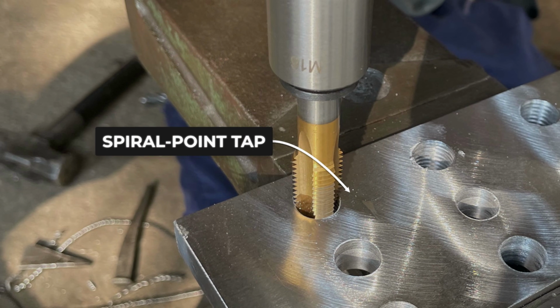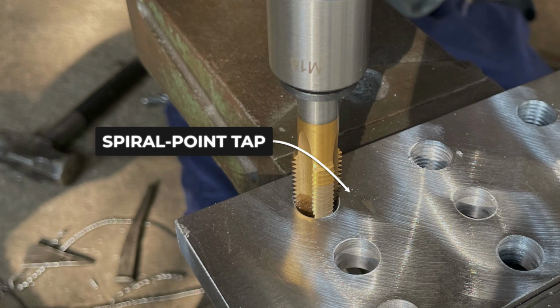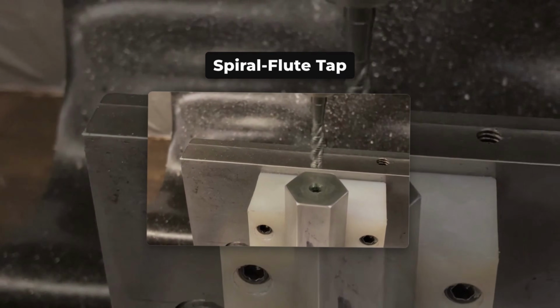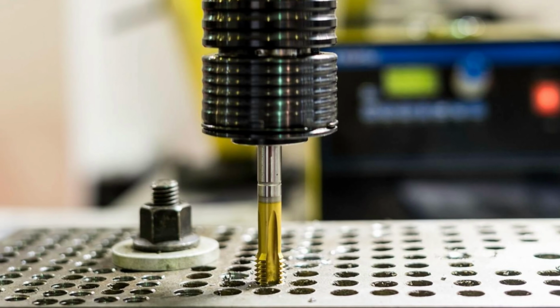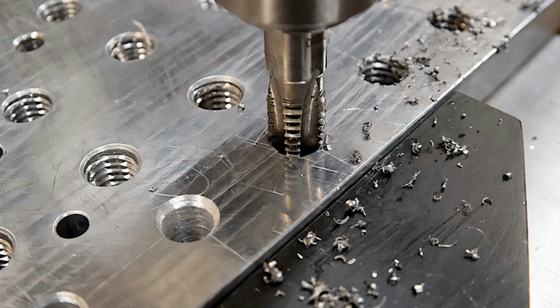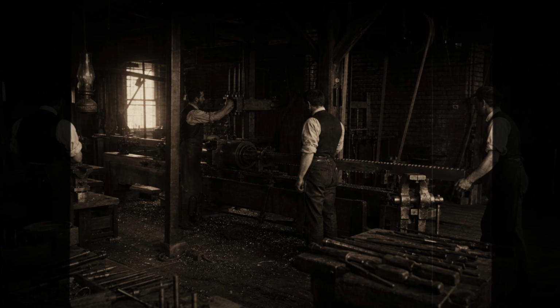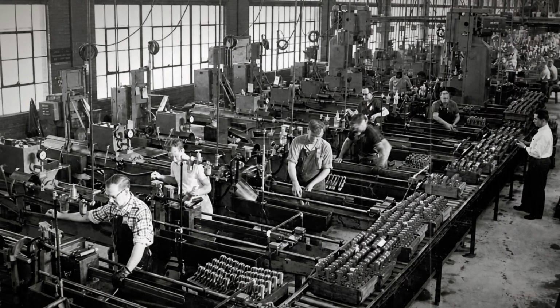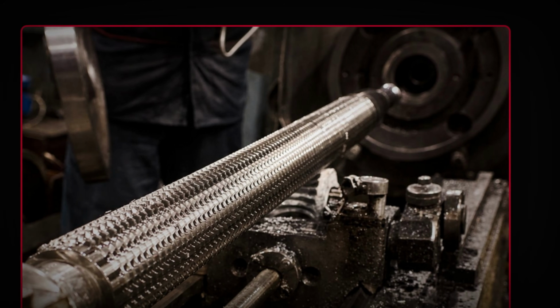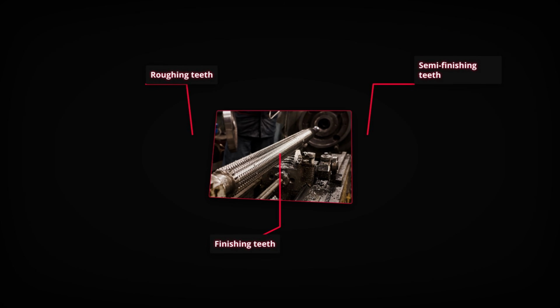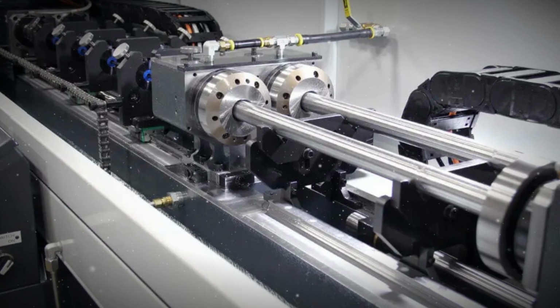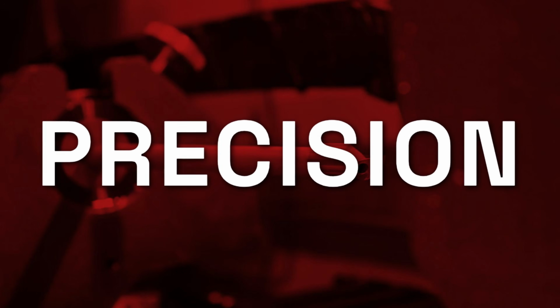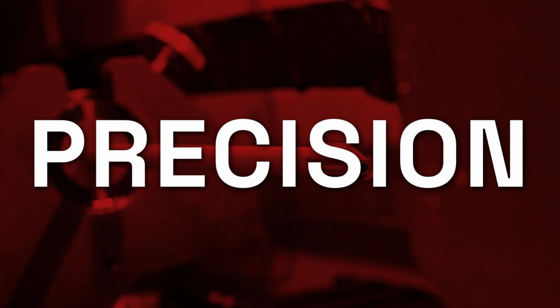Taps split into families: spiral point taps that fire chips forward through the hole, spiral flute taps that haul them back out of blind ones, and forming taps that cut nothing at all, cold forging the thread into the wall for a stronger profile, and several times the tool life. Broaching came out of the 1850s keyway shops, and after the First World War, it took over rifling gun barrels, a gang broach pulling roughing, semi-finishing, and finishing teeth through the bore in a single stroke. Gun drilling was born in barrel making too, coolant pumped down a single flute carbide tool that holds a straight bore at depths past 300 diameters.